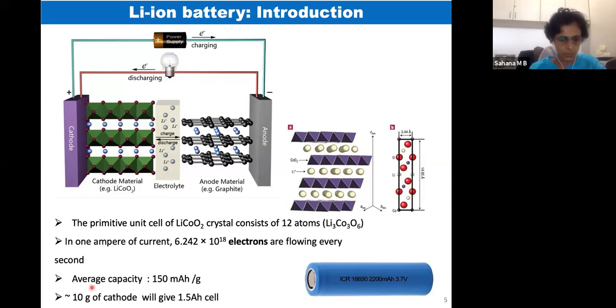That's way less, right? So basically, 1 ampere current means... if you see a battery, the marking here, this blue one down, it's 2.2 ampere hours. So the meaning of 2.2 ampere hour is this battery can give you 2.2 amperes for 1 hour. So think of the number of electrons, or the number of lithium cobalt oxide molecules, that need to go into the structure. Because 1 ampere current is 6 into 10 to the power 18 electrons flowing per second. So we need this much to flow for 1 full hour.